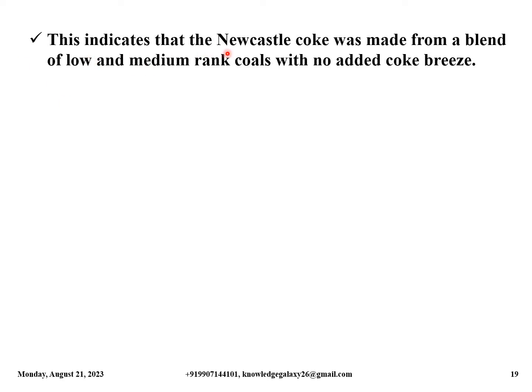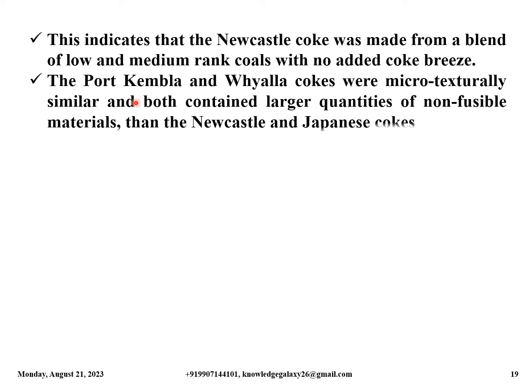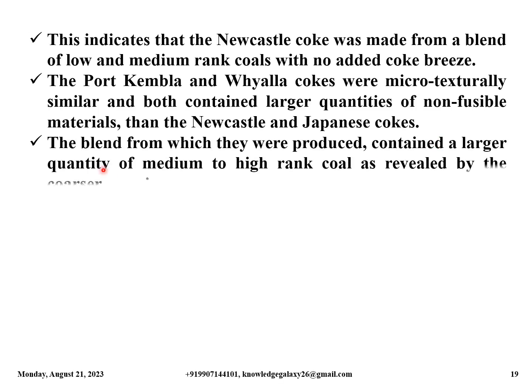This indicates that the Newcastle coke was made from a blend of low and medium rank coals with no added coke breeze. The Port Kembla and Whyalla cokes were microtexturally similar and both contained larger quantities of non-fusible materials than the Newcastle and Japanese cokes. The blend from which they were produced contained a larger quantity of medium to high rank coal, as revealed by the coarser mosaic textures.